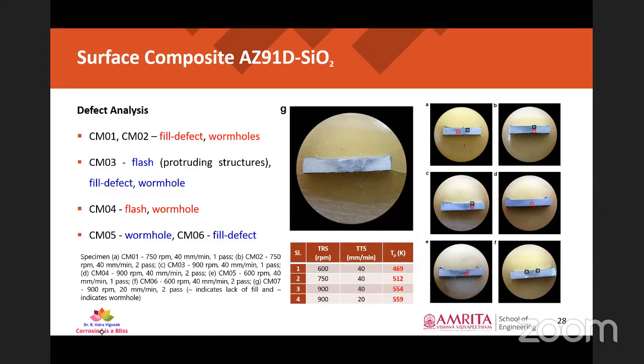CM04 had flash and wormhole, which was processed at 900 rpm and 40. They too had defects related to wormhole and fill defect. Okay, and when you process the same material at 900 rpm, 20 mm per minute, and for 2 passes, we have not observed any defects internally and externally too. There were no flash, and there is no fill defect, and there is no wormhole. So that picture is shown as G over here, where we could observe there is no defect that is present in the material in the lateral section and in the longitudinal section too.